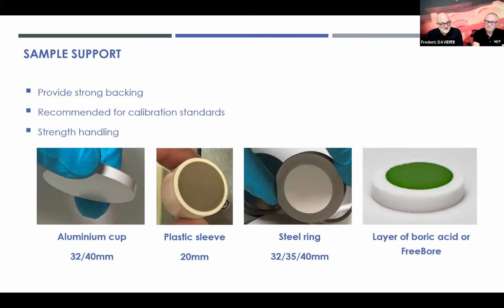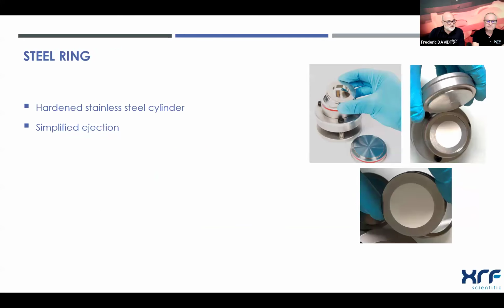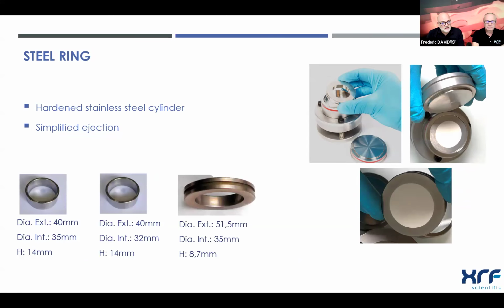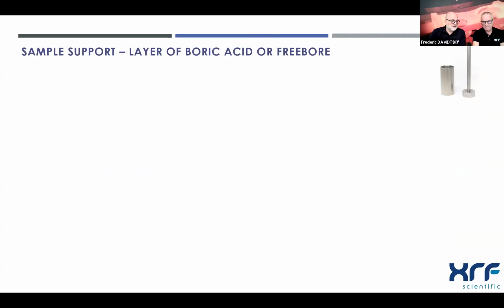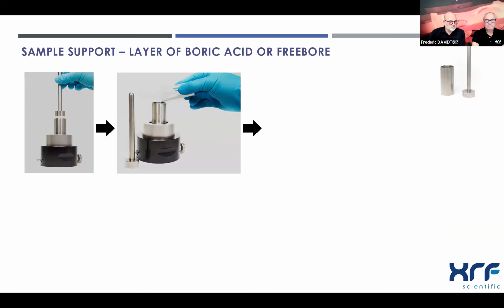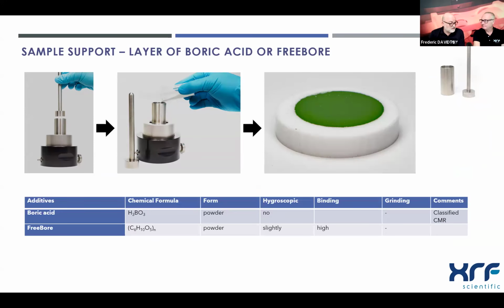And like you explained already, the coat of boric acid, or the backing of boric acid, or FreeBore. FreeBore because in some labs we don't want to have the boric acid anymore because it's classified CMR. So the steel rings, just to show you the different types of steel rings you have available. It mainly depends on the type of automated pressing machine you are using and adapted to the spectrometer. So they can be reused. You can remove the powders after and reuse the steel rings. And then the sample, like you already explained, the layer of boric acid or FreeBore. And so we have some tools to prepare that. And again, it's made for the binders like boric acid or FreeBore.